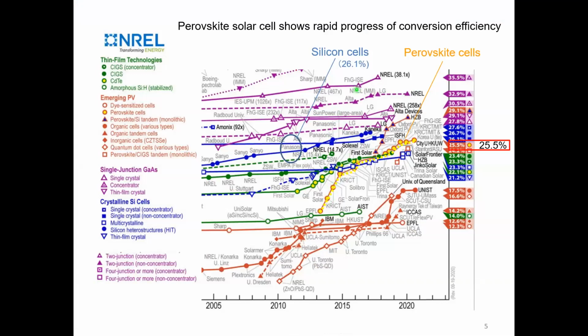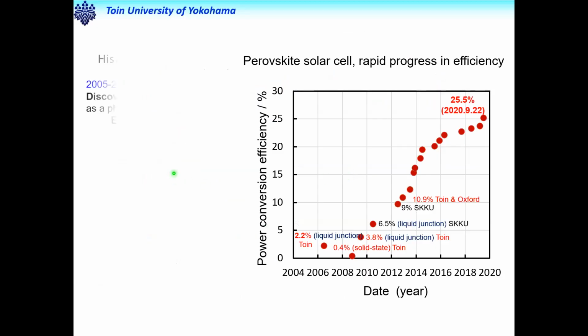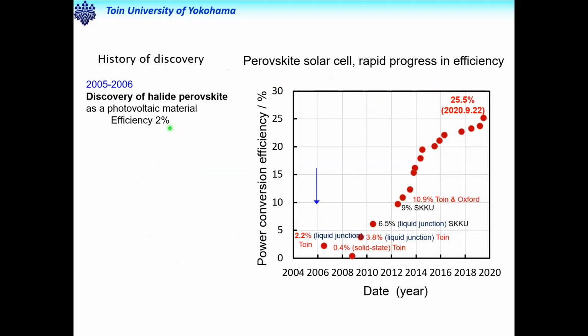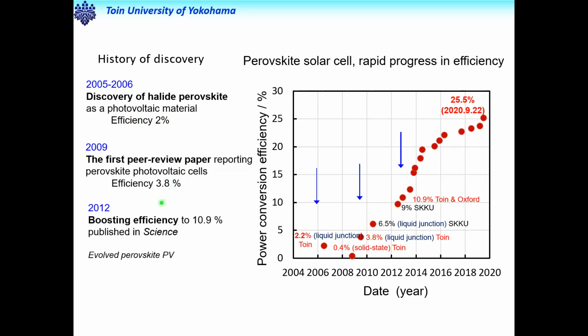When we look at the recent progress in the efficiency of the perovskite solar cell, plotted in yellow, we can compare it with silicon. Silicon's efficiency is still increasing slowly, but perovskite development started in 2012 and the efficiency rapidly increased. So we can see how quick this progress took place. We first discovered this halide perovskite semiconductor for photovoltaic application in 2005 or 2006. Efficiency was still low, 2%. Then in 2009, we published the first peer-reviewed paper reporting a perovskite photovoltaic cell exhibiting 3.8%, still low efficiency. But in the next three years, by 2012, the efficiency was boosted to beyond 10%.